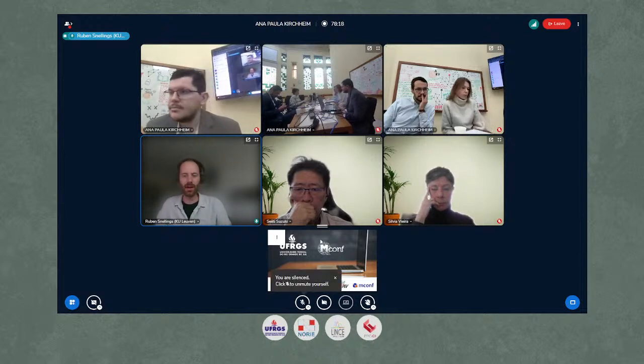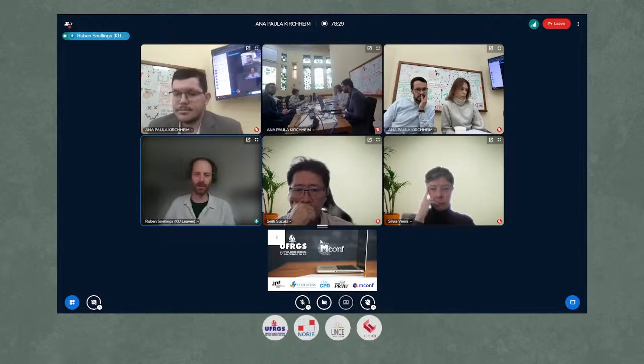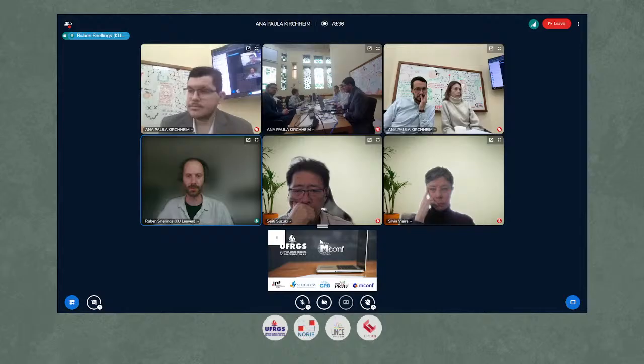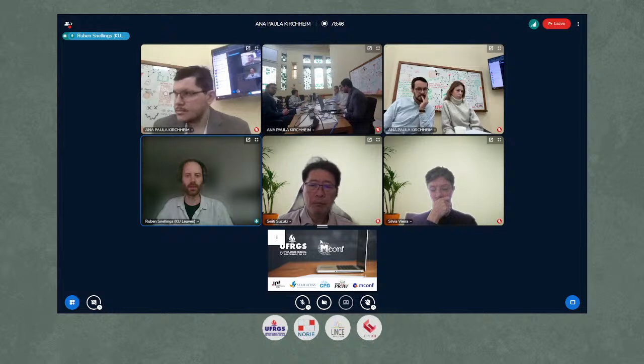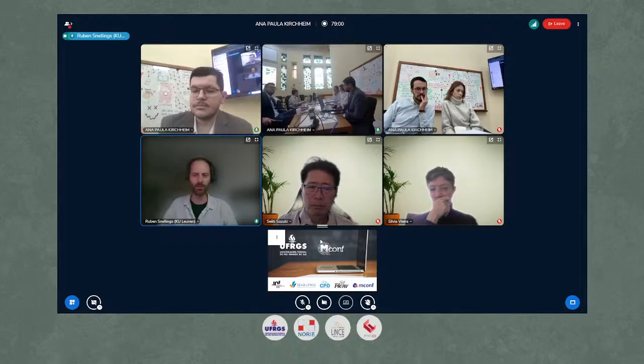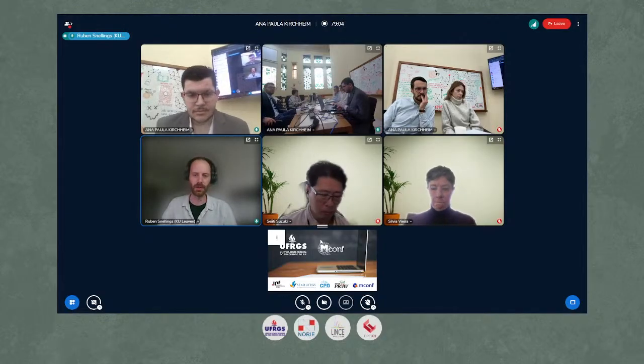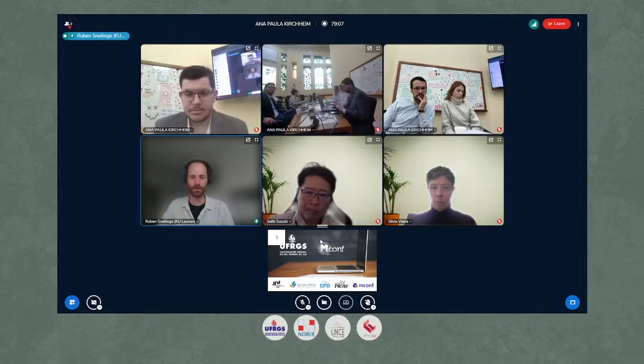Because in Europe, these are prescriptive limits that have at some point been defined out of, maybe, compromise, but at least there must have been some underlying data saying this is safe and it is not so safe to go above. In Europe, for instance, the magnesium oxide limit is 5%. So, can you comment? Because it's interesting, also in terms of development of new binders. Maybe in the Brazilian experience, there is no issue with soundness or expansion when we have more sulfate or more magnesium oxide. Or do I see this wrongly? And is there another test you should do so you can be sure that there is no risk later?